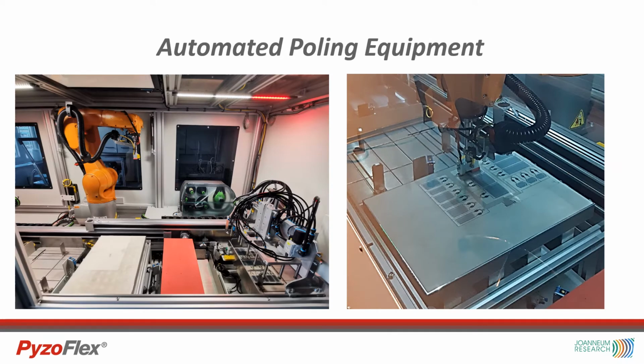In this context, it is also important to mention that the poling process is a functional testing of the sensors, and thus a quality control of the printing process. So meanwhile, we do the poling in an automated form with robots, as you can see here. This poling step can also be used to calibrate each sensor to a specific sensitivity, meaning a specific remanent polarization value.